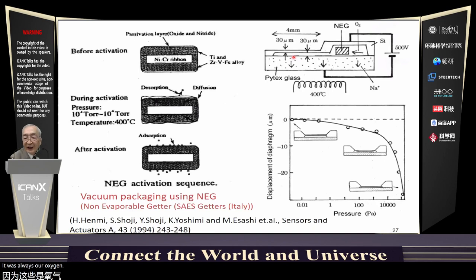A vacuum cavity can be obtained by using a non-evaporable getter in it. The getter material is activated during the anodic bonding at 400 degrees centigrade and absorbs the oxygen gas in the cavity. We made the structure shown in the upper right. This has a thin diaphragm and the non-evaporable getter in the cavity.